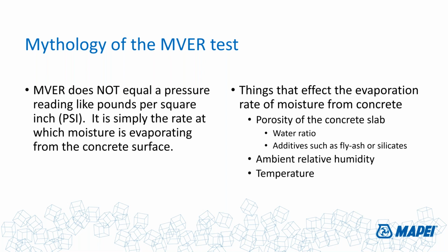And that's the second thing. Additives such as fly ash or silicate materials can also affect the porosity of the concrete slab. Fly ash particularly will make that surface very glass-like and will totally reduce the amount of water vapor evaporating out of a concrete slab, because the pores are much smaller and tighter.